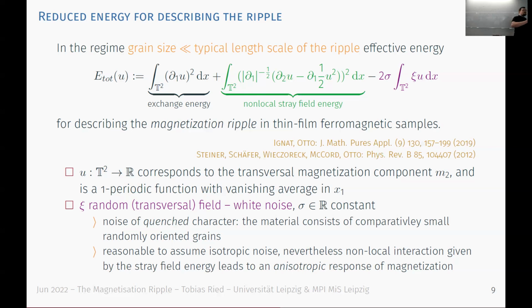Remember that the magnetization was a unit vector, so m1 squared plus m2 squared has to be 1, which means if m1 is 1 and we just look at small oscillations, we can expand the square root of 1 minus m2 squared, and essentially arrive at this energy. And then effectively the anisotropy energy can be shown to basically act like a field on the m2 component, so a field on u, where the field is given essentially by the random field I showed you in the sketch here.